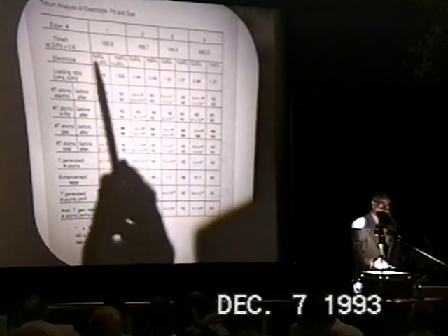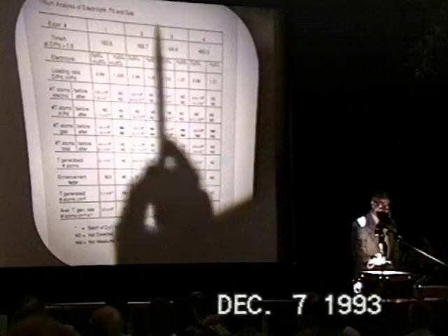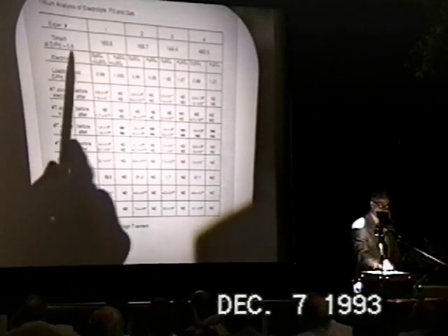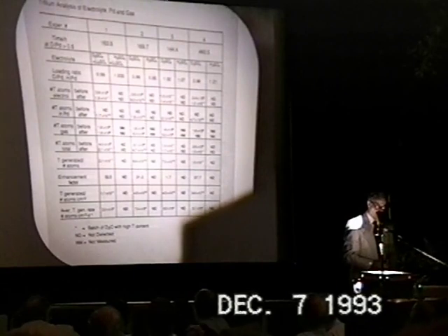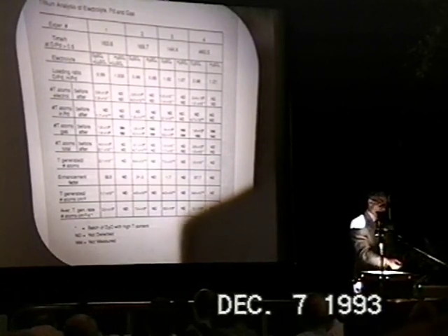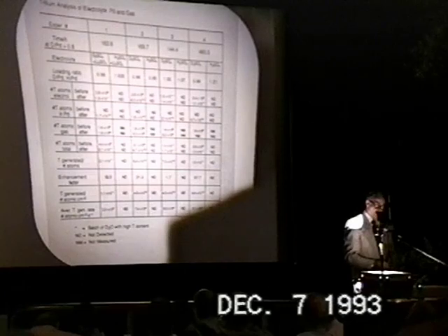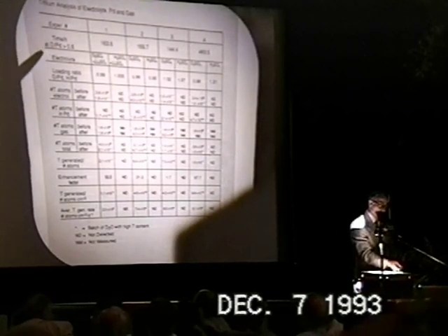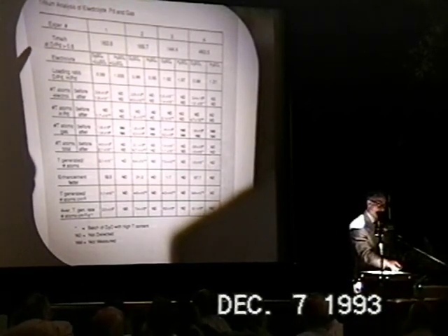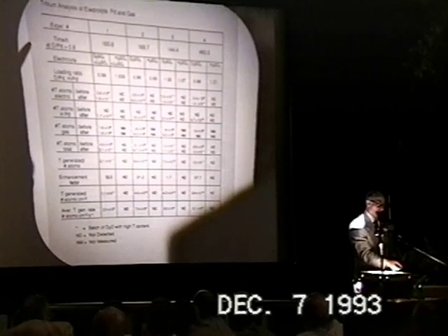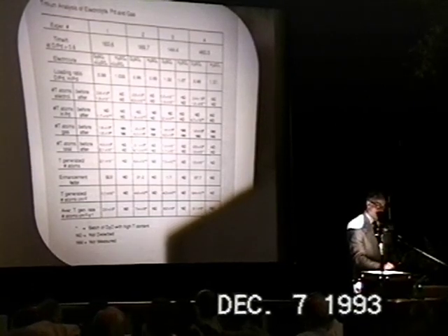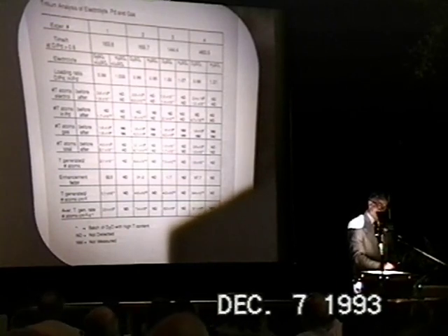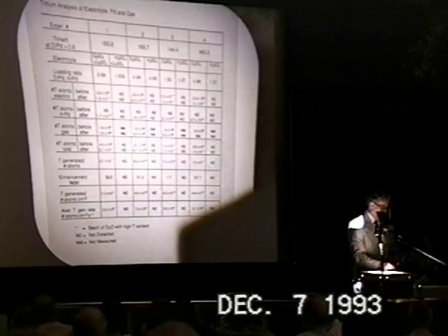Let me just point out the time of electrolysis counted from the time on that we obtained a loading ratio of 0.8. The significance of 0.8 is clear to many of us. We have observed in separate experiments that no tritium had been formed when the loading ratio was lower than 0.8, and it appeared that 0.8 indeed is a critical threshold value above which only we were able to generate tritium